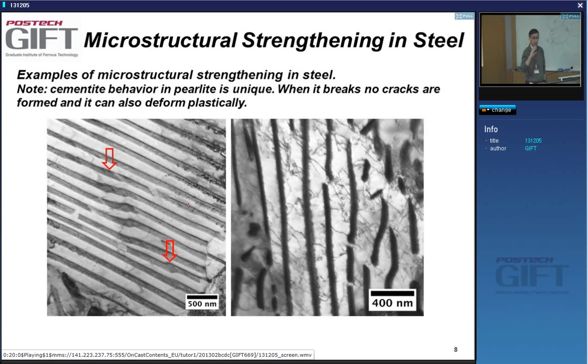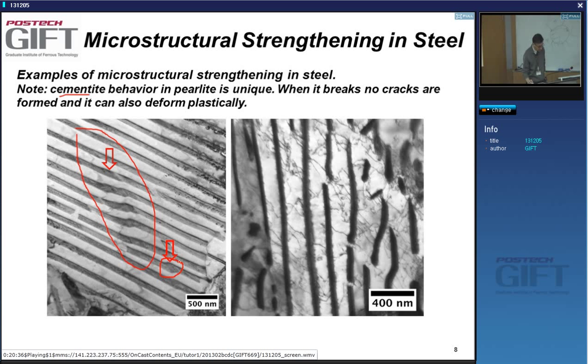I want to show you this very interesting phenomenon about cementite behavior. It's impossible to measure the properties of cementite in bulk — it has no plasticity in bulk. But if you look at a pearlite lamella, you can see there is a whole region that has been sheared with no fracture and no delamination anywhere. Here you see another very nice shearing situation with no fracture or delamination. You can see the deformation and even the breaking of the lamellae, but there is no void formation. Very interesting and unique properties in terms of plastic deformation.